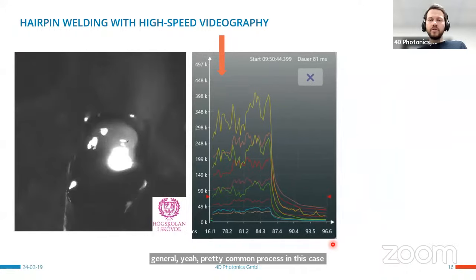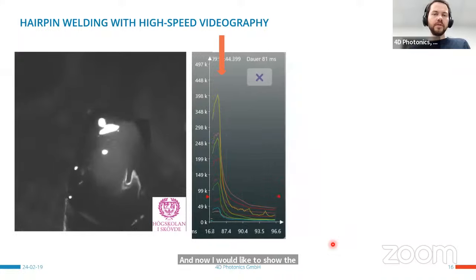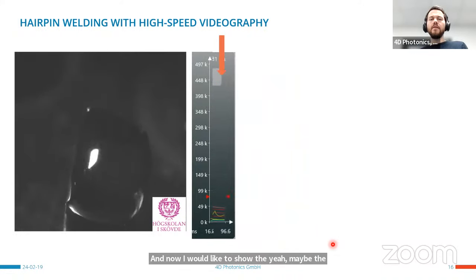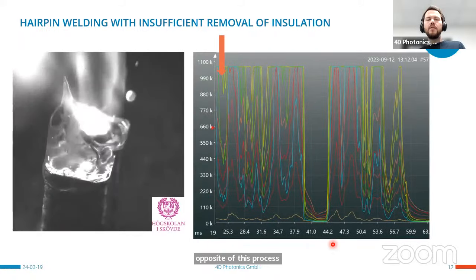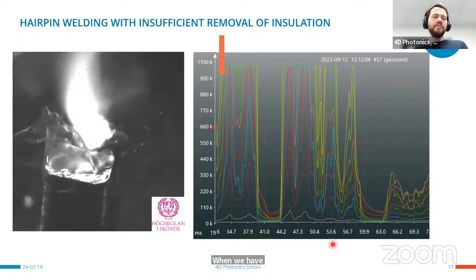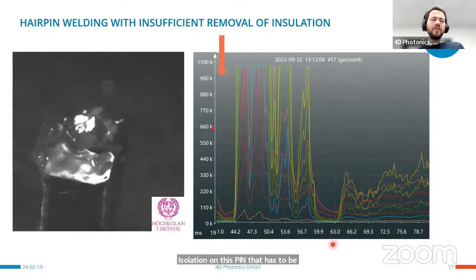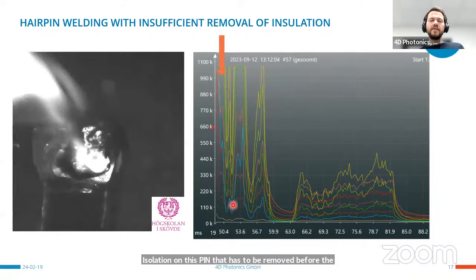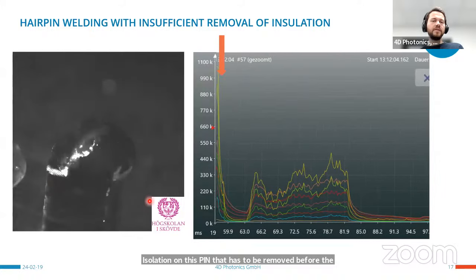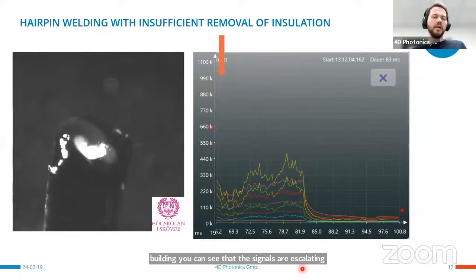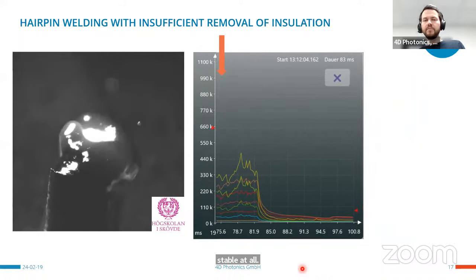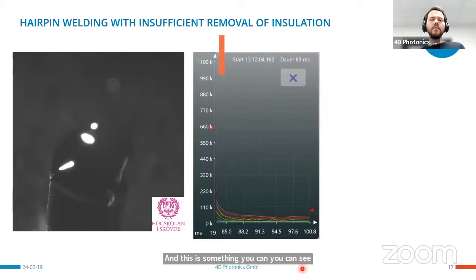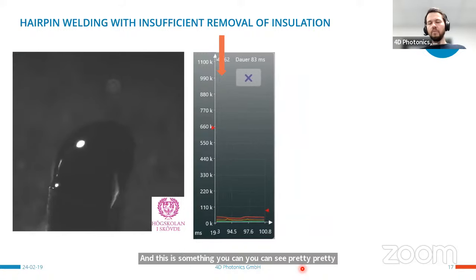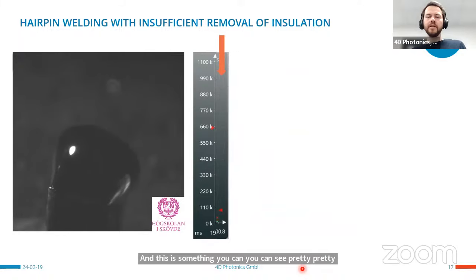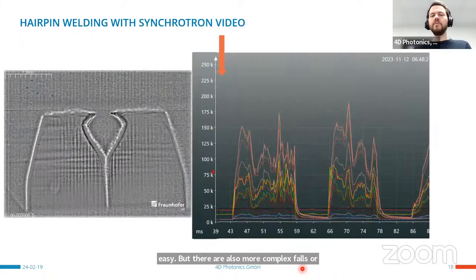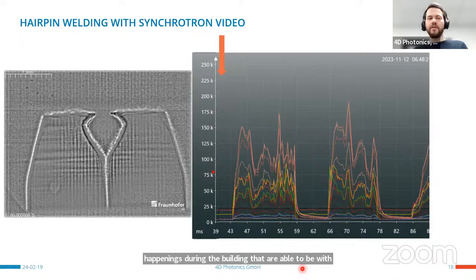And now I would like to show, maybe, the opposite of this process. When we have some isolation on this pin that has to be removed before the welding, you can see that the signals are escalating completely, and also you can see the process is not stable at all. And this is something you can see pretty easily. But there are also more complex faults or happenings during the welding that are visible in our data.